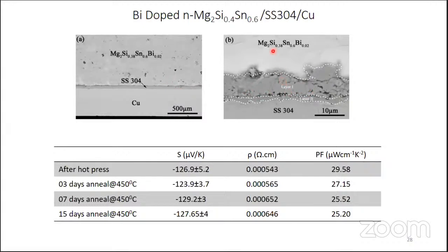So once we put this in, this is the thermoelectric material, this is the electrode, and in between is SS304 as the diffusion barrier layer. Here you can see the as-prepared, as-bonded condition, and after hot press. Even after 15 days, the joint is stable. The resistance is comparable. The power factor is also comparable. So this joint is now perfect. It works up to 450 degrees Celsius without undergoing any thermophysical or thermochemical change. It shows very high stability. So this joint will work in the device.